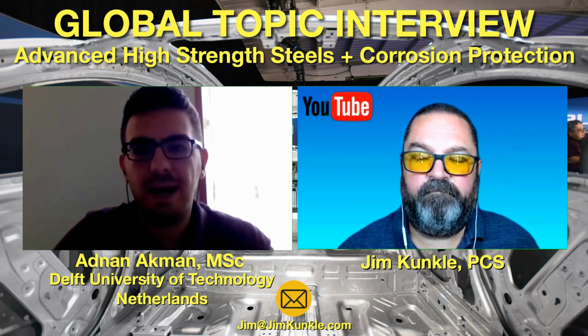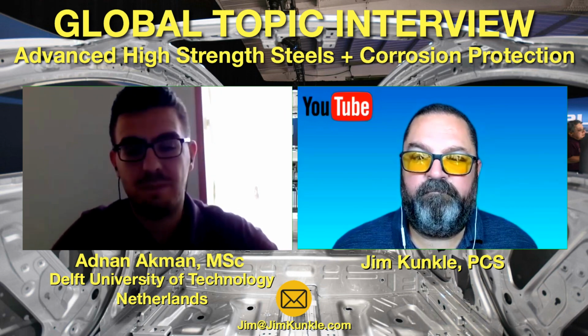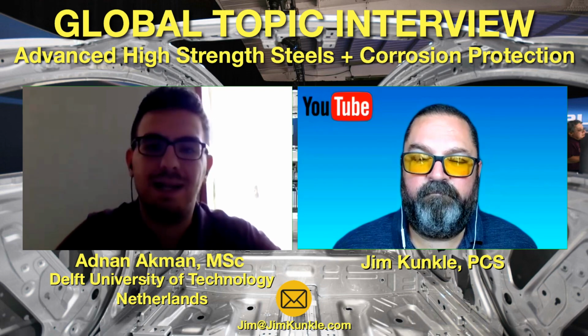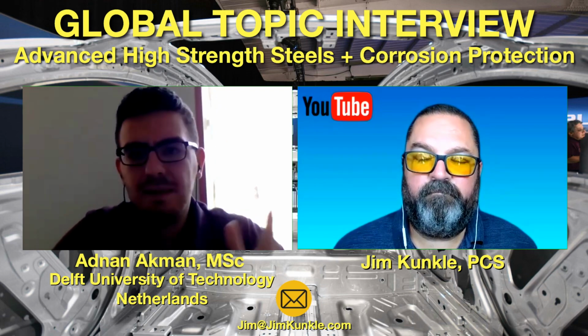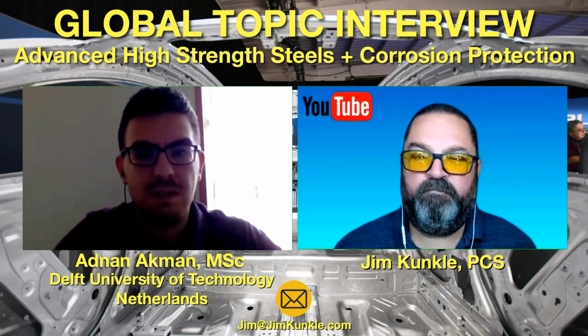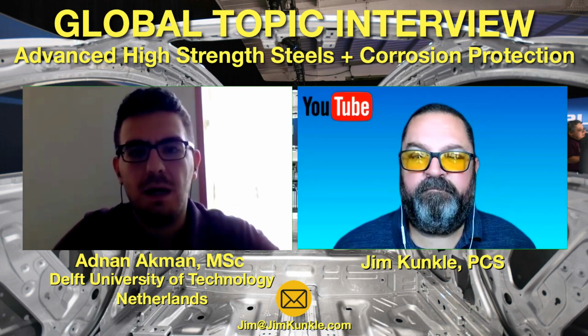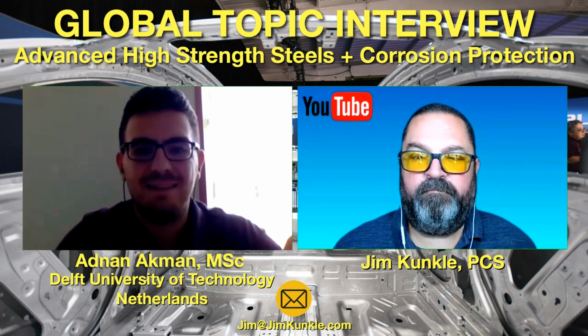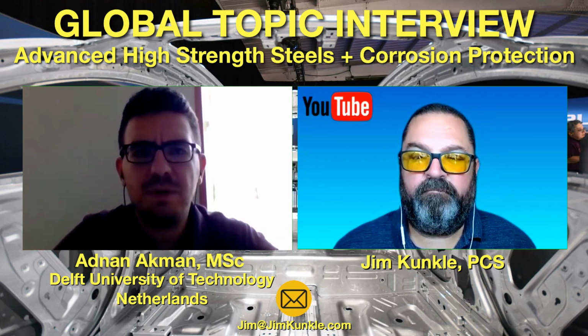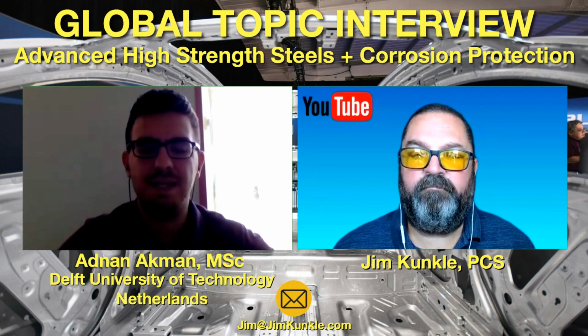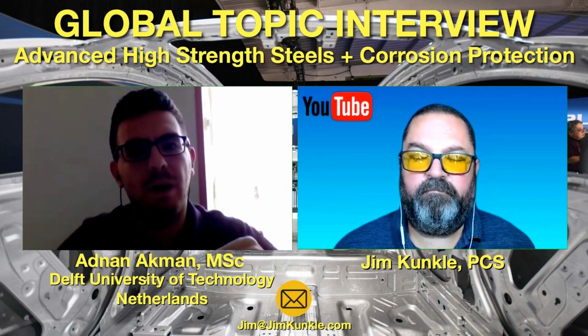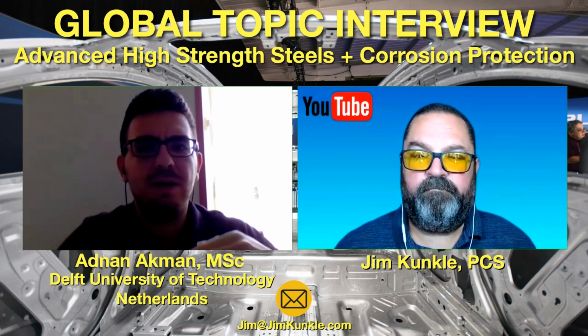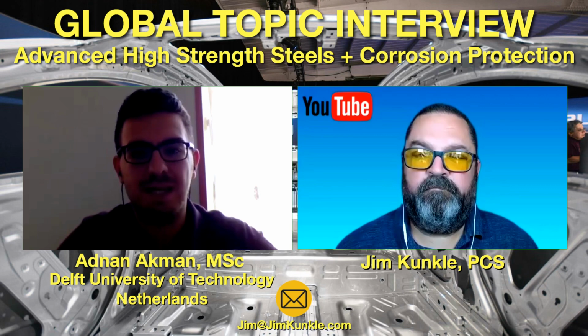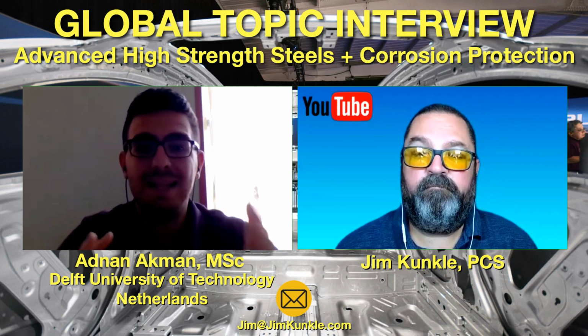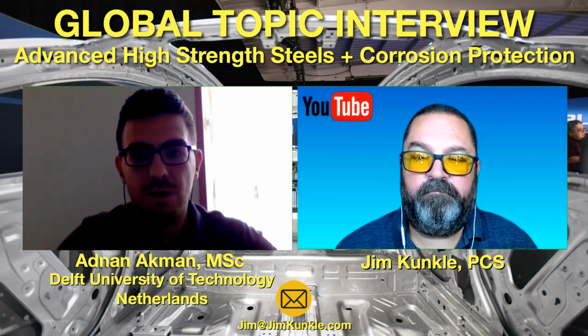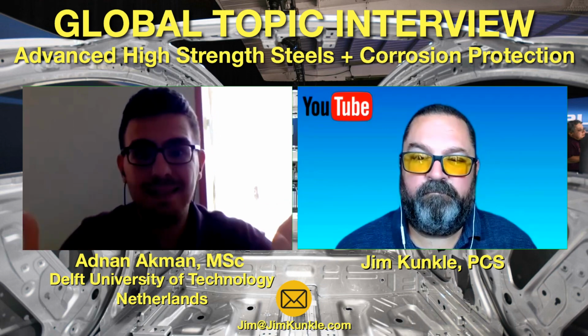So we can classify the galvanizing technique into three groups, as we mentioned. These are hot dip galvanizing, electrogalvanizing, and galvannealing. Hot dip galvanizing is a quite popular technique nowadays, also in industry. We are dipping our steel component into a zinc bath. The processing temperature is around 450 to 500 degrees Celsius. If there is excess zinc, you can remove it with air knives. After some time, the zinc cools down on the surface, and when you remove your steel, you have a zinc layer on top of it.